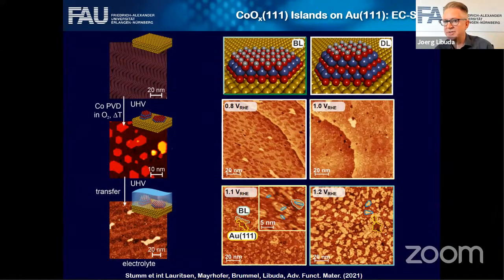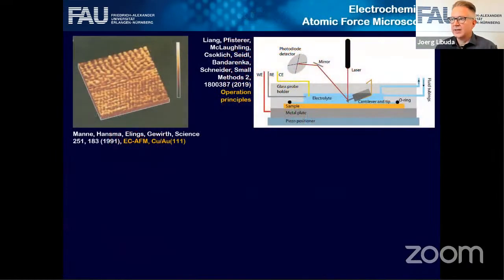So the bias changes, and as a result here in these images, the contrast changes. And in these images here, the islands appear as depressions, whereas under this different potential, the islands appear as protrusions. And that's a consequence of the fact that we're not free to choose any bias in this experiment. So that's a big challenge. Now, if you don't want to use the tunneling experiment, what else can you do?